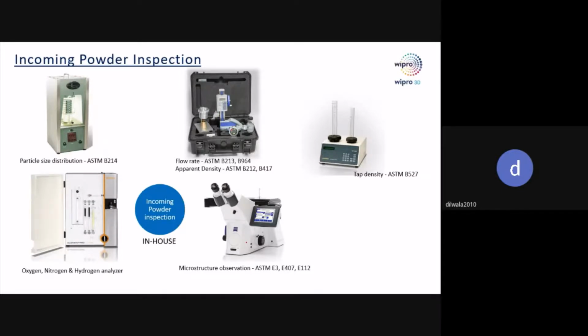Then comes tap density. In this, we tap it for a predefined number of times and then check the density. We continue this activity till we see there is no more change in density even after increasing the taps. Then we measure the density and decide whether the powder is accepted or not. This parameter governs the mechanical properties of the part.